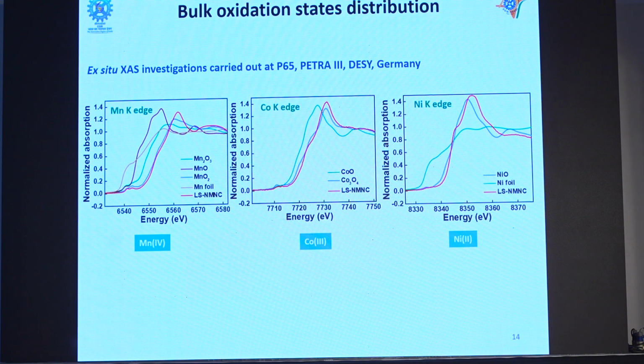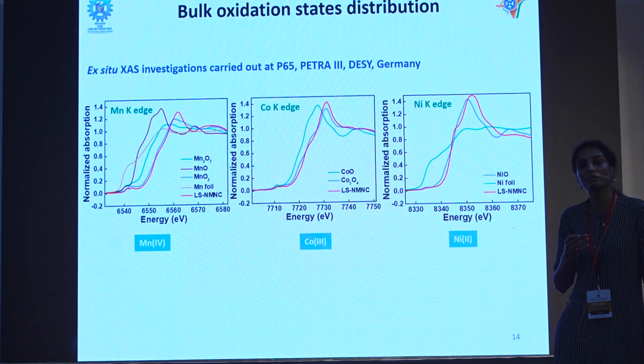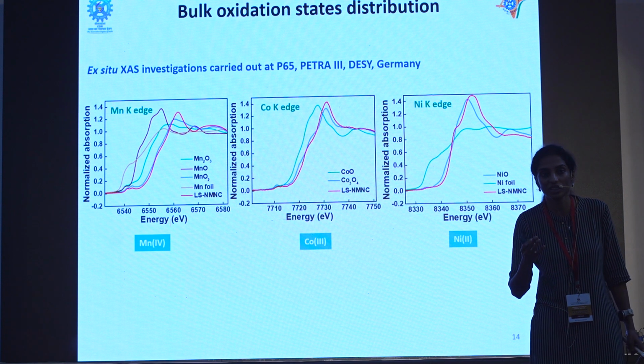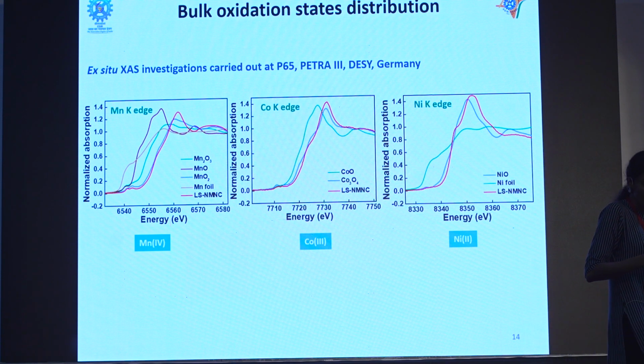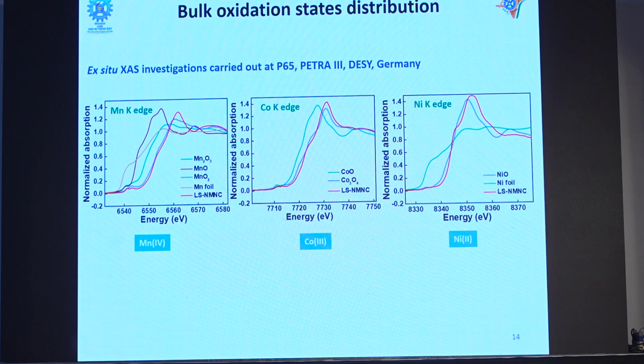And most of the time what we have observed is that when we analyze our material with XPS, we see all divalent cations on the surface, but it doesn't mean we are seeing any electrochemical reactions from the divalent cations from the material. So that's why we use X-ray absorption spectroscopy in transmission geometry. It's a bulk technique. We can get the oxidation state of your bulk.